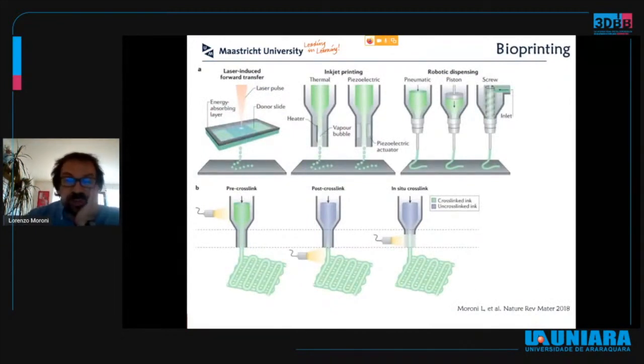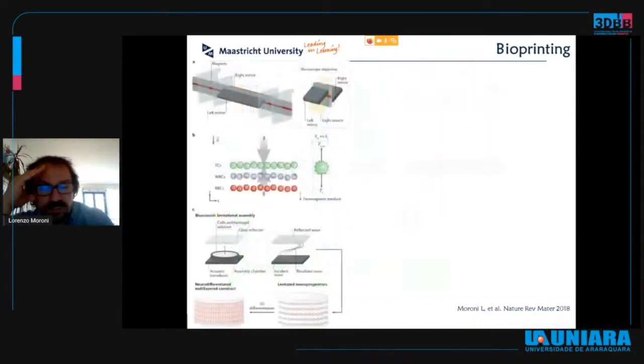Alternatively, what we could do with bioprinting is deposit in different layers, or within the same layer, different kinds of fiber properties, such as shell-core fibers, and different kinds of cells. Now, in the case of bioprinting, a number of technologies have been developed. The three most used are laser-induced forward transfer, where droplets of these cell-laden hydrogels are deposited on a stage, or inkjet printing or robotic dispensing, where again, either by droplets or by continuous filaments, we can deposit cell-laden hydrogel constructs or actually cell spheroids without the use of hydrogels.